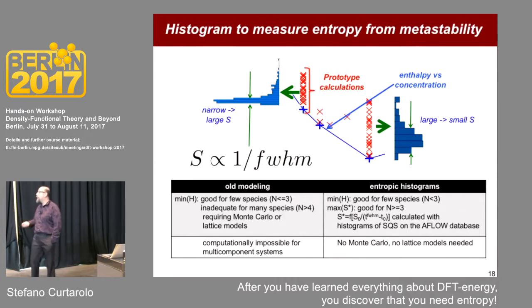You can wait shorter. You use the Wang-Landau method. This works very well if you do not have any phase transition. And if you guess right the shape of the initial distribution of states, you can get the entropy very quickly. Or you use these new methods like the nested sampling method, which also allow you to jump between different phases. Okay, this is some technicality, but the bottom line, the entropy is a very difficult quantity to get,